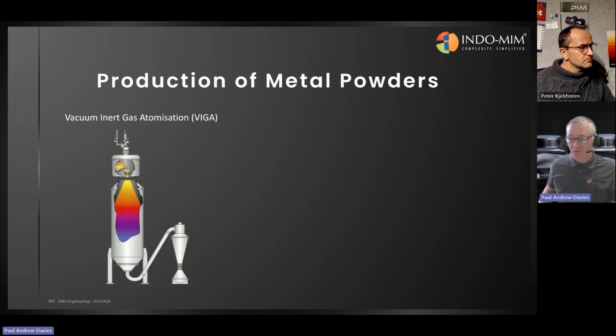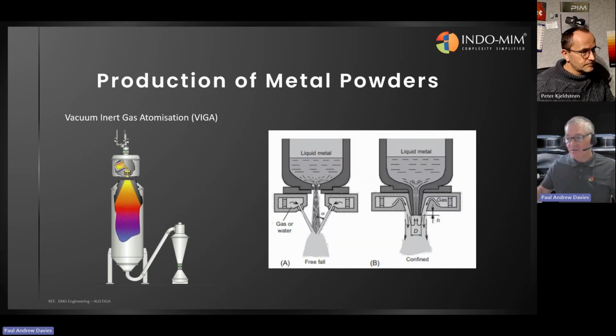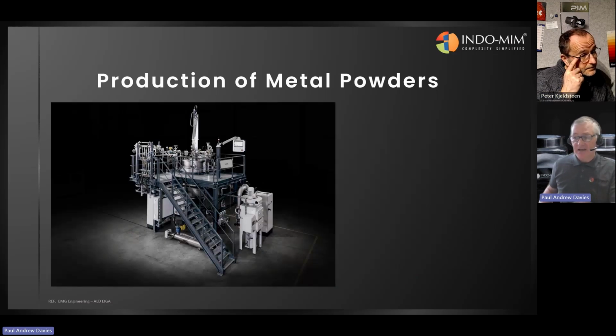Schematic of the atomizing process. In this case, it's a top pouring induction furnace into a tundish and then atomized using different gases, as you can see here. Often the tundish is then free falling into a free fall atomizer. We generally use confined atomizers to make finer powder, I would say. And that's the kind of scale as the plant, as you saw earlier in the video.